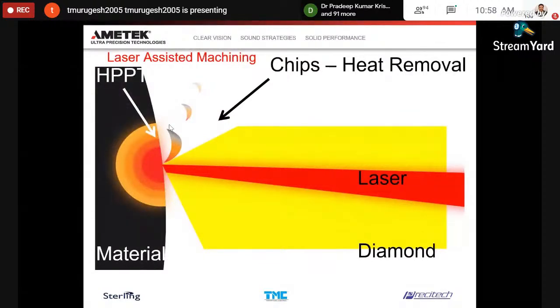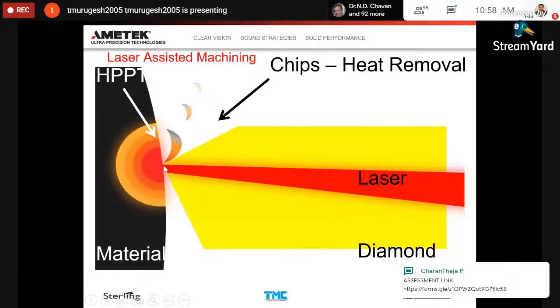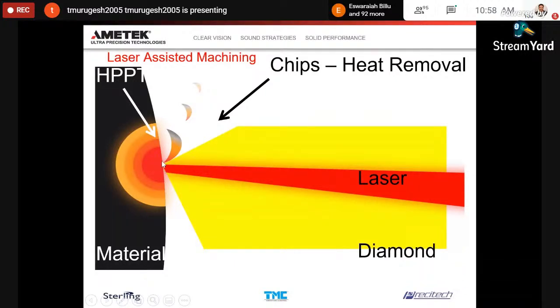If you ask me about the principle of how it is possible to remove material for ceramics, hard ceramics or hardened steel, for example. If you look at this tool, the yellow part shows a diamond tool, in which there is a micro groove of the order of maybe 0.1 to 0.5 diameter, and the laser is passed through this diamond tool or the orifice, and the laser is incident onto the surface. And at this surface, the material becomes soft. So when the material becomes soft, the diamond starts removing the material, making machinability much easier, which was almost impossible before.